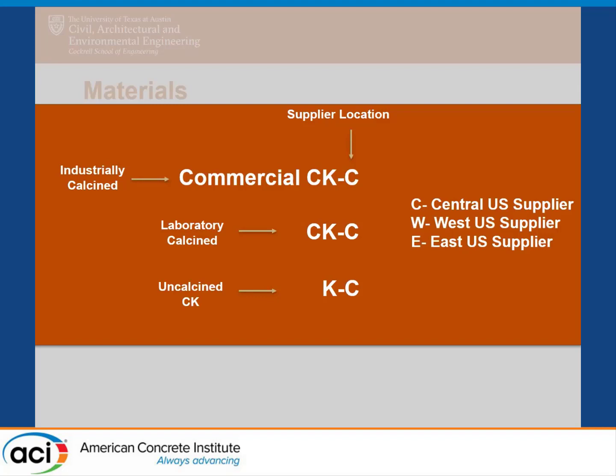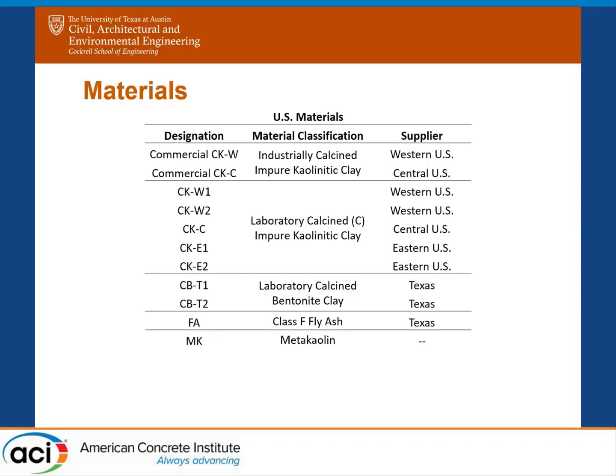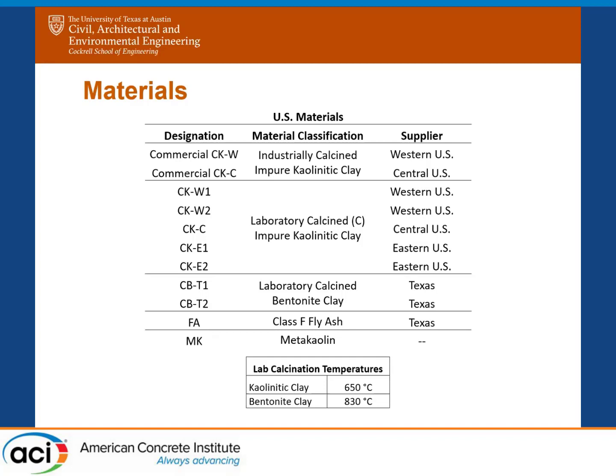And then the C, W, and E correspond with the supplier locations across the US of Central, West, and East. And then the Class F fly ash and the commercial metakaolin are used as a control and a comparison because we're a little bit more familiar with those materials traditionally. So the lab calcination temperatures in our laboratory for the kaolinic clays were 650 degrees C, held for 1 hour, and then taken back down to room temp. And the bentonite were at 830 degrees for an hour.